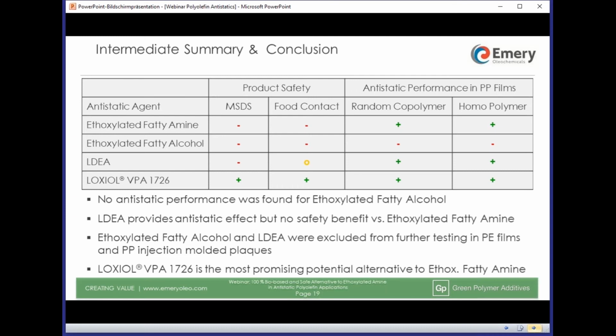Antistatic performance-wise, I consider ethoxylated fatty amine, LDEA, and LOXIOL VPA 1726 good solutions for PP films. Ethoxylated fatty alcohol does not work at all. So how to continue? We decided to exclude ethoxylated fatty alcohol from further testing. It is not safe, and we found it is not a well-working material in PP films.